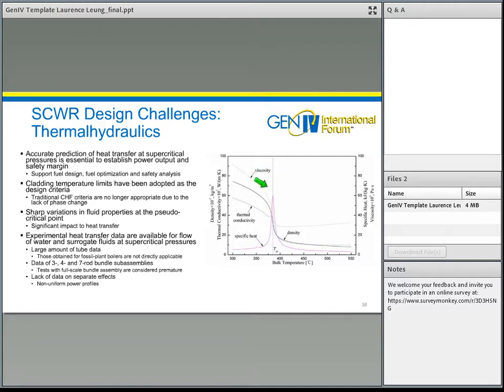You can see the properties drop sharply in this area, but not as sharp as the discontinuity when you have a phase change. This is the variation of the density and the viscosity. The specific heat, on the other hand, is at a low value at low temperature, then jumps up and increases sharply at the pseudocritical point, and after that it decreases and goes to a low value again at high temperature. Because of this sharp variation in property, it has a very significant impact on the heat transfer characteristic.